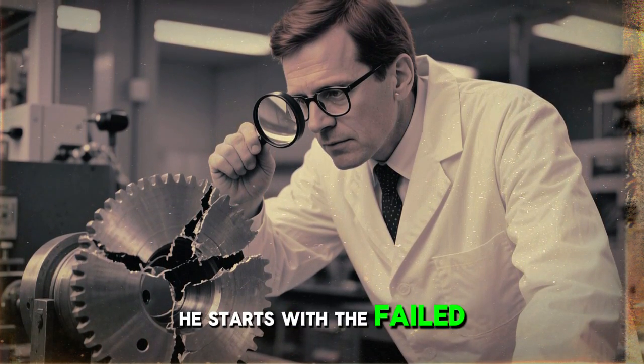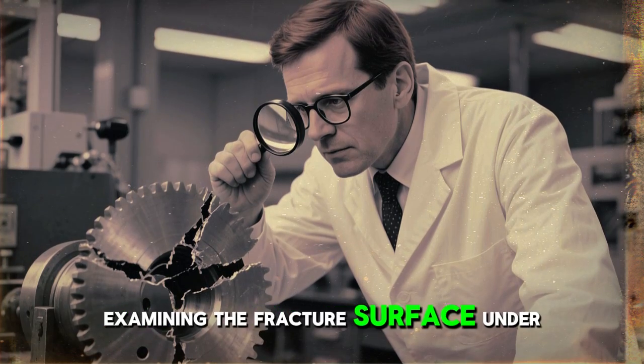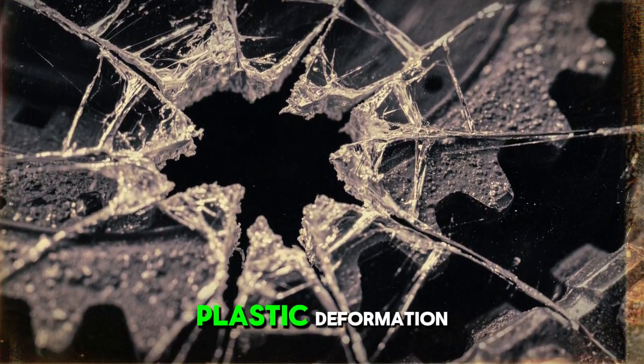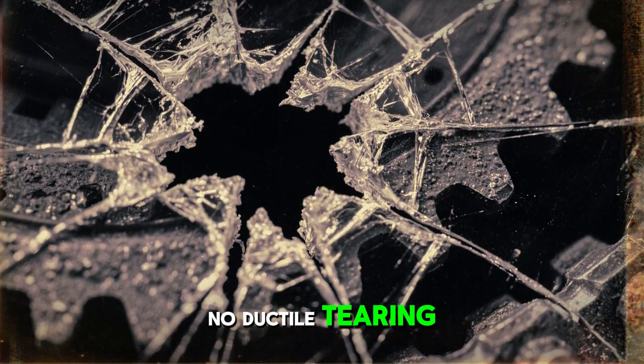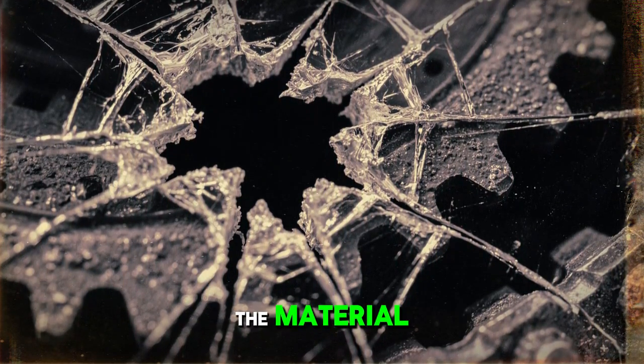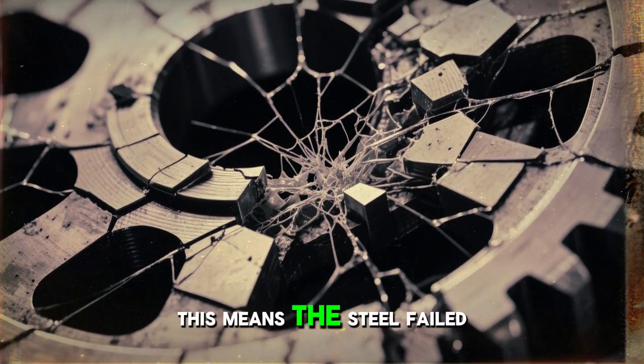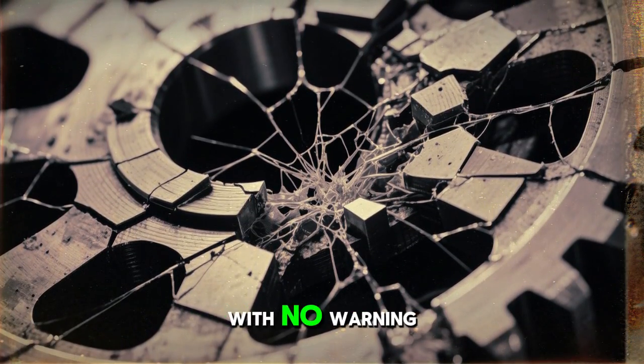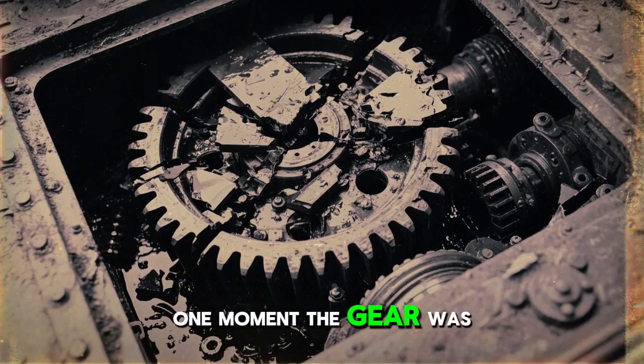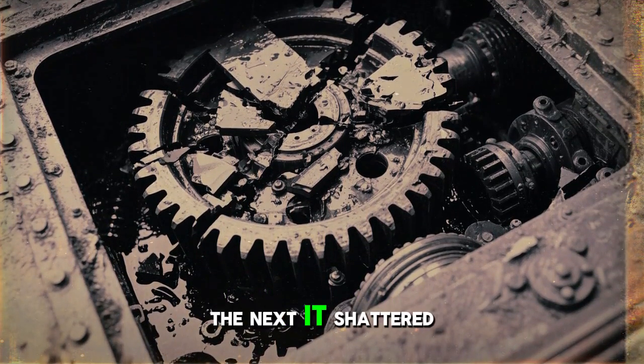He starts with the failed gear, examining the fracture surface under magnification. The break is brittle. No plastic deformation, no ductile tearing, just a clean snap through the material. This means the steel failed suddenly under stress with no warning. One moment the gear was transmitting torque, the next it shattered.